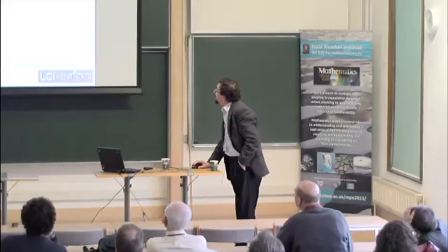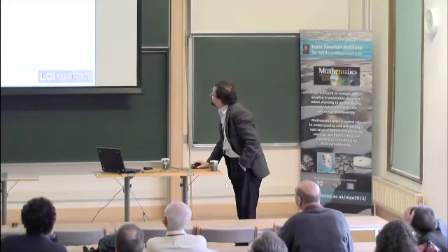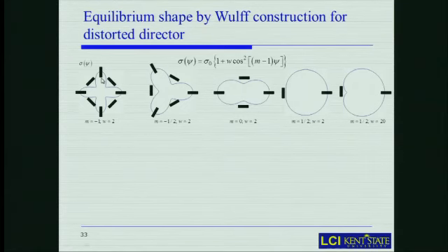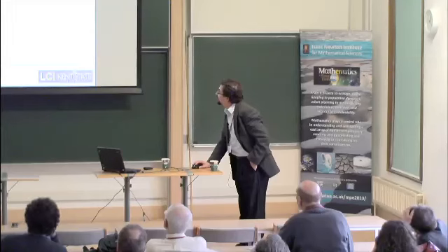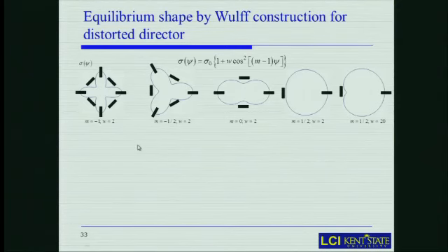So if the disclination has the topological charge -1, then you have 4 points where the director is perpendicular to the interface. But the equilibrium alignment is tangential. So that means that in these points, you would have a maximum of the surface tension. And the surface tension in the polar plot is simply the distance from the center to this point. For tangential orientation, the surface tension is much smaller, and this distance is much smaller.